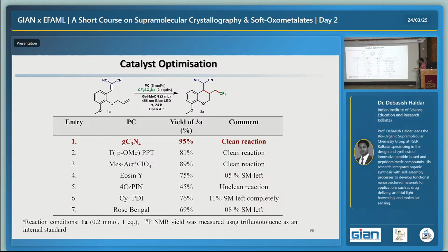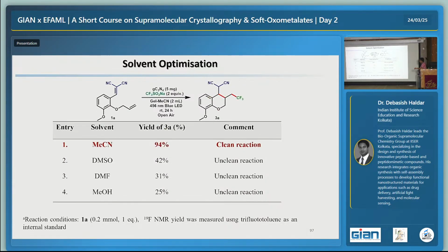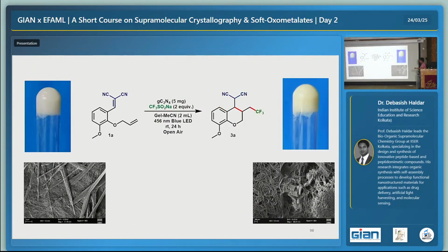So we have done all the optimization with different photocatalysts, and what we figured out is that g-C3N4, that photocatalyst, is working fine. We have also tested many solvents, and in acetonitrile we are getting a very nice product, 94-95% yield, and this is what is happening. So this is the gel containing all the reagents, and after the light irradiation the gel is intact, and that's why we are getting 95% conversion.